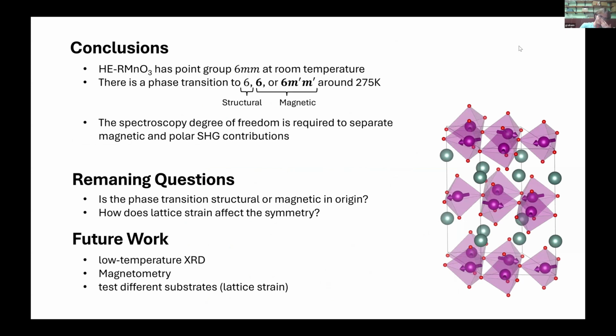But to sum things up, we've confirmed that the SHG reflects the 6mm point group. So that is in order. And we have a phase transition just below room temperature that may be structural or magnetic. Now, the magnetic possibility would be exciting because this is very high temperature, but that's also the reason it's more